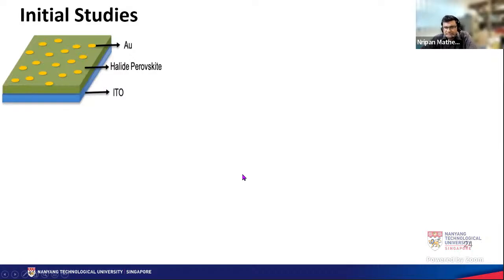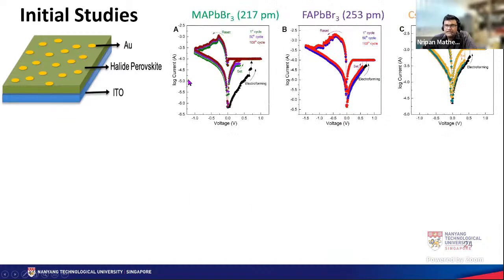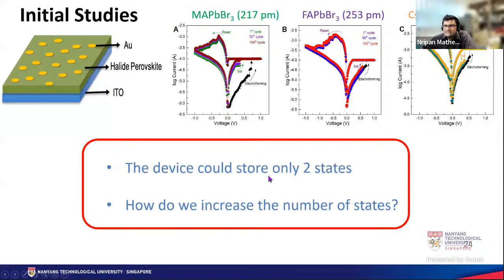In our initial studies on utilizing it for memristors, we just put a metal electrode directly on top of the halide perovskite, which was directly on top of an ITO electrode. We compared 3 different types of perovskite. MA is methylammonium lead bromide. FA is formamidinium. These are both organic ions. And cesium is, well, the metal cesium. When you make this kind of simple architecture, you are able to form a simple 2-state system, which is good, but not necessarily so useful for neuromorphic because you want to have multiple states.